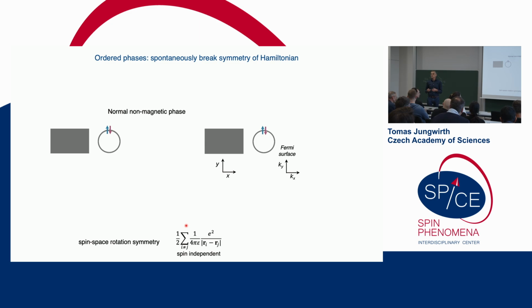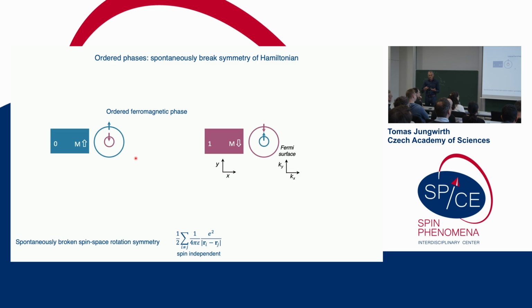And so is the normal phase of the system, where it's not in the ferromagnetic phase but still in the normal phase. When we look into the momentum space, we see that there is no spin dependence, so there is still the full spin rotation symmetry preserved, the symmetry of the parent Hamiltonian. That changes when we go into the ferromagnetically ordered phase, because in the ferromagnetically ordered phase, what you see is that in the Dirac space we develop a net magnetization, and now we can have a state in which magnetization is pointing up, or we can have a state in which magnetization is pointing down. So we break the spin rotation symmetry, and those two states are not equivalent, and they can, in spintronics, represent the two logic states of the binary bit, for example.